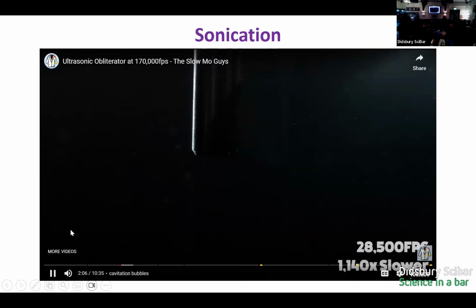It's okay. So essentially this is a slow-mo video of sonication occurring in a solution. So this tip is vibrating really, really fast and essentially creating these voids. They're bubbles in the solution. And they effectively grow and then collapse. And when they collapse, they pull in the solvent, and that stretches out the polymer chain that's with it. So it's quite a violent process, actually, if you look at it in slow motion. So we're creating this really turbulent flow in the material to look at how this stretches our polymer chains.